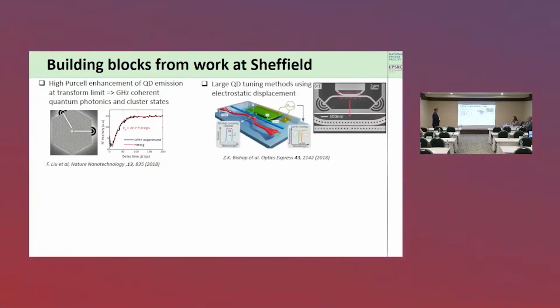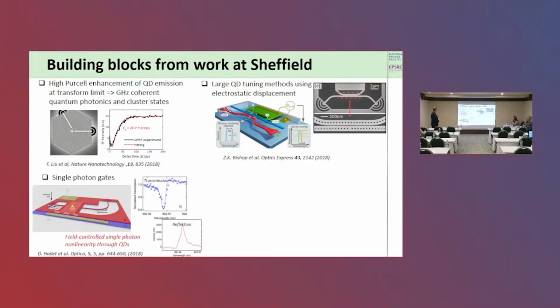Also, these quantum dots are tunable, and there's a variety of methods, including applying an electric field to the dot, but also there's some interesting options in using electrostatics and using proximity effects of different waveguides. So here's an example of two waveguides, and by applying an electrostatic force, we can move them relative to each other, and that gives us a significant tuning of the optical emission of the dots. That allows us to do things like tune the dots in and out of high Q cavities. And this is then very useful for manipulating the single photons that we have.